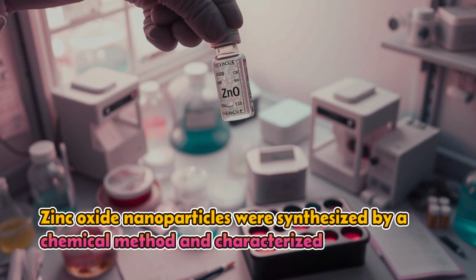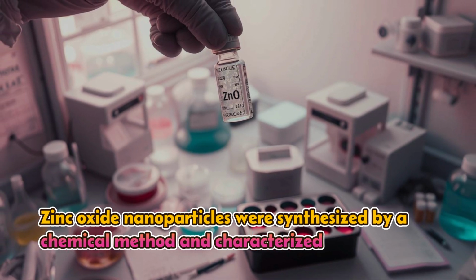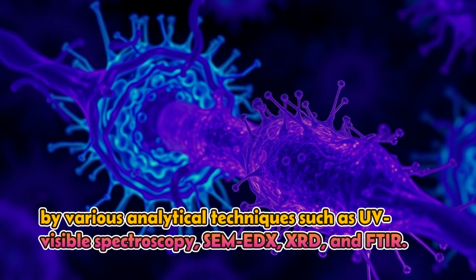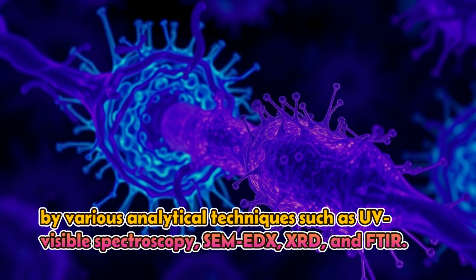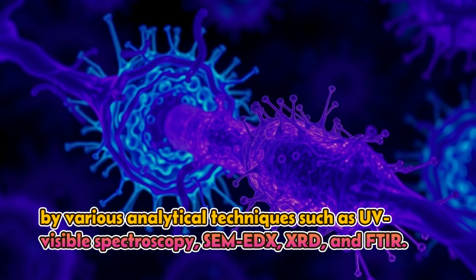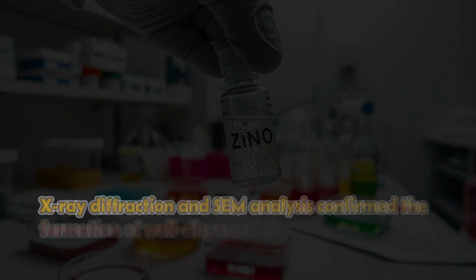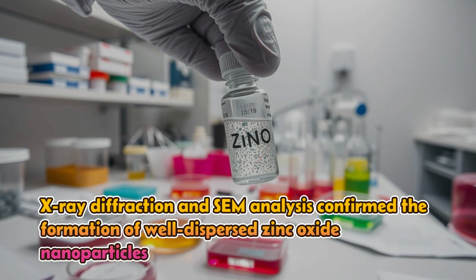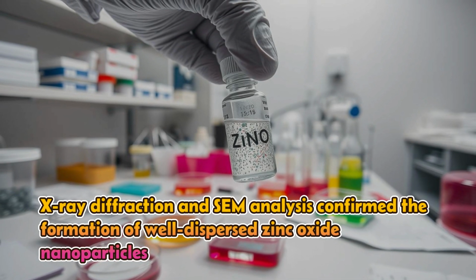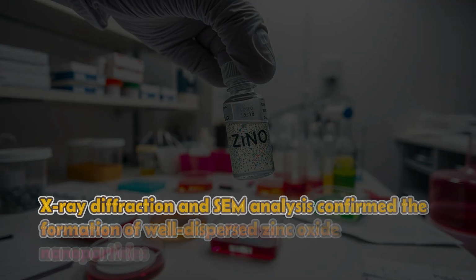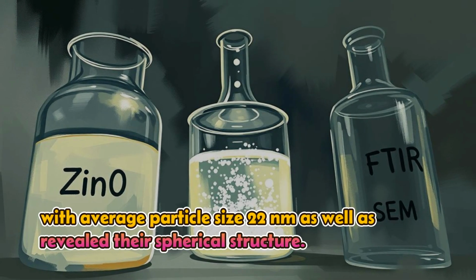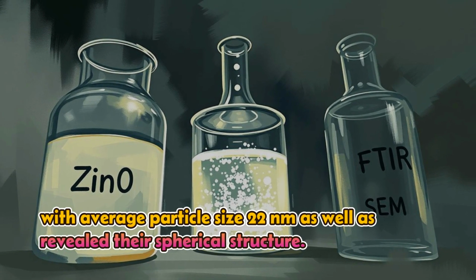Zinc oxide nanoparticles were synthesized by a chemical method and characterized by various analytical techniques such as UV-visible spectroscopy, SEM-EDX, XRD, and FTIR. X-ray diffraction and SEM analysis confirmed the formation of well-dispersed zinc oxide nanoparticles with average particle size 22 nanometers, as well as revealed their spherical structure.